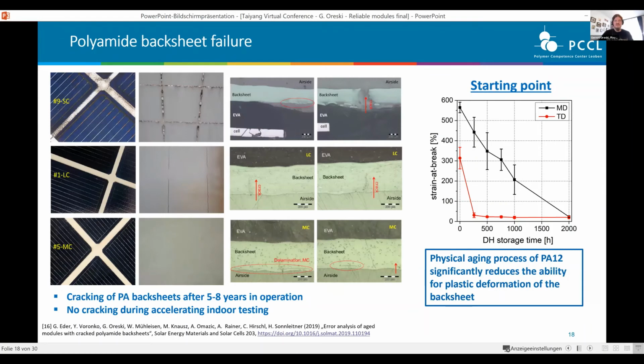Just a short story, what's the starting point? For this polyamide 12, we have a very unusual physical aging process. As you can see on this strain at break tensile test results, already after very short time exposure to heat, we have a significant reduction of the ability of plastic deformation of the backsheet. So we have strain at break values around 15, 17%. So that's very, very low.